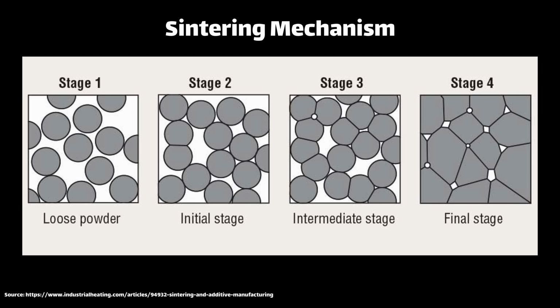And when you add water, it washes all away. This is fine. There's nothing wrong with that. There's a lot of composites that are essentially an inert filler surrounded by some type of binder or glue. That is essentially what carbon fiber and fiberglass is, but it's not quite sintering in my opinion. So if option 2 is the case, I don't think this is really sintering at all. I think it's just a composite.